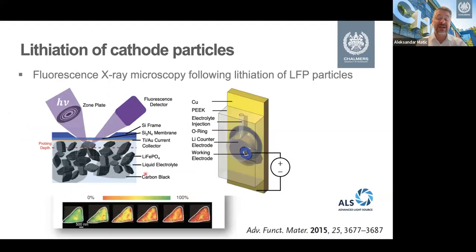On the cathode side, here is a really nice example from the Advanced Light Source in the US, where they use fluorescence X-ray microscopy to follow the lithiation in lithium iron phosphate particles. So through this microscopy, you can actually understand the chemical state. The chemical state while you're inserting lithium into the particle will then give you a sign of how charged it is. So here you can see going from 0 to 100, you basically change the color of the color map on the particle.